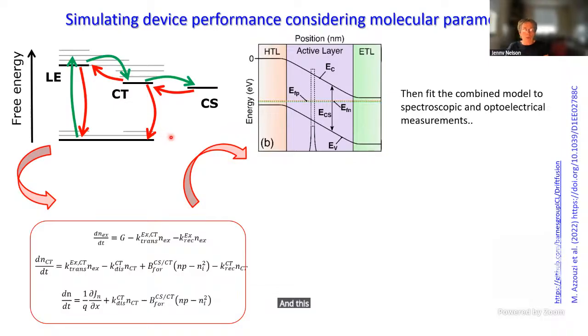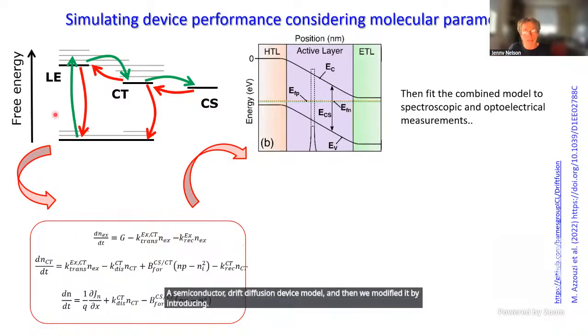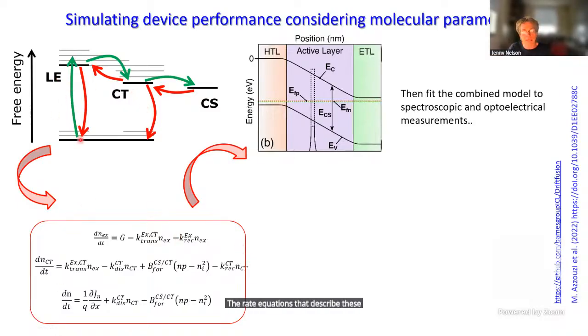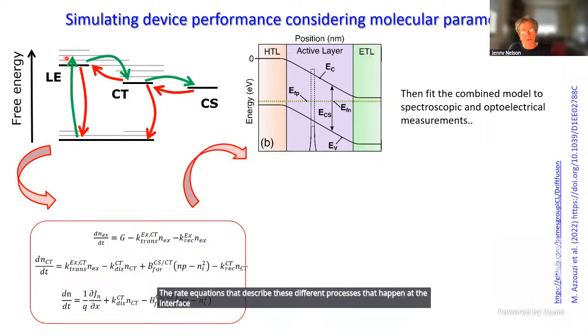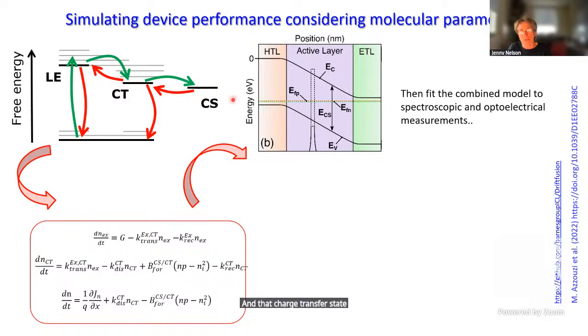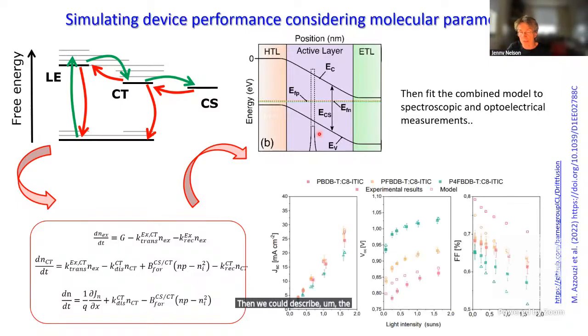And this was something we were able to do. We took a semiconductor drift diffusion device model, and then we modified it by introducing the rate equations that describe these different processes that happen at the interface, where you generate an exciton and it may or may not separate, and that charge transfer state may or may not deliver independent electrons and holes. And then the backward processes are possible. It all satisfies detailed balance. So when we put those equations into the formalism for a semiconductor device, then we could describe the entire system.